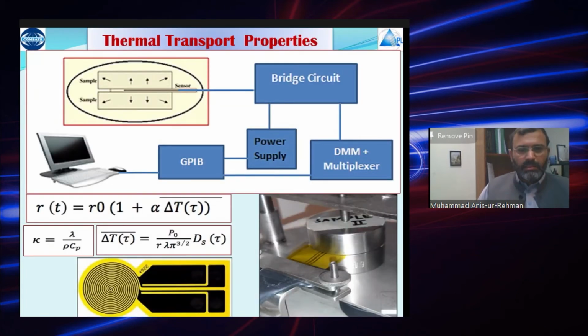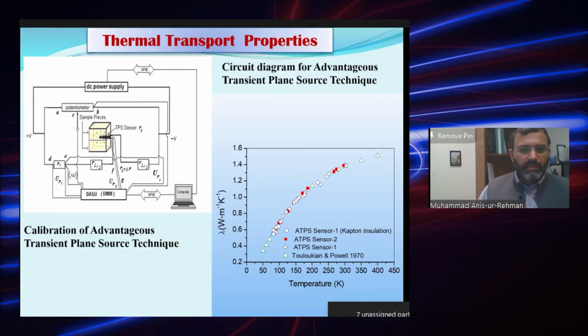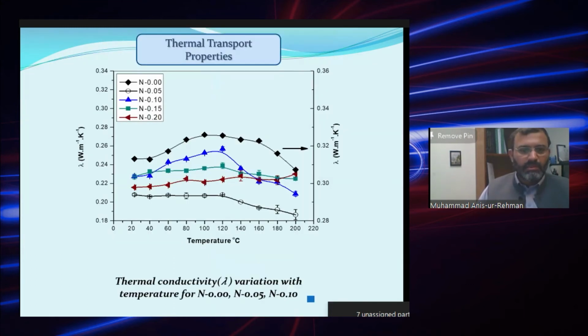The thermal properties were lastly investigated by the transient plane source method. That was a system in which a sensor is sandwiched between two identical sample pieces, and then the data is obtained. We have calibrated the system and compared the data of the quartz, and we see that the data obtained by our system was very much in line with the reported value.